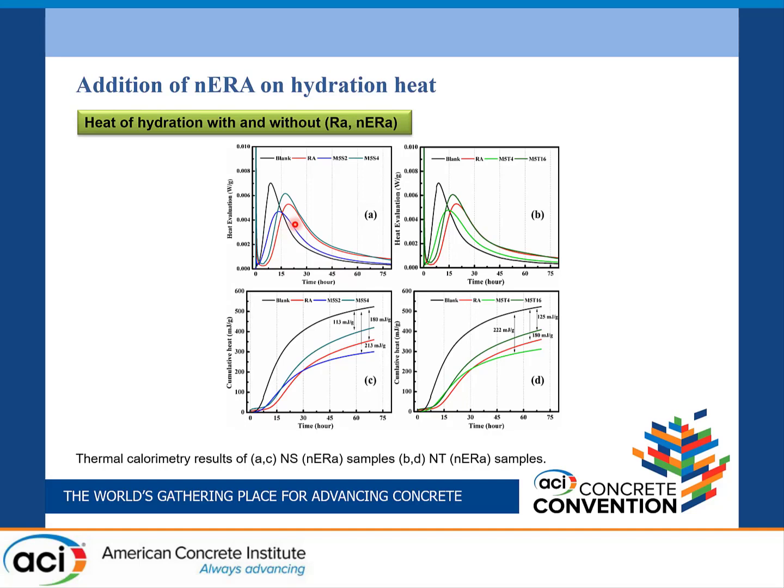It seems that nanoparticles do not lead to higher hydration, but improve the hydration dynamics. Here we see that the nanoparticles can enhance the heat of hydration, but do not lead to higher heat of hydration; they improve the hydration dynamics. After this, we did some water absorption tests.